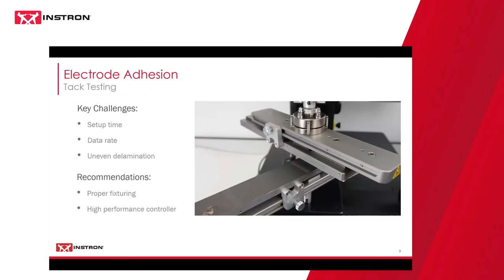So another type of electrode adhesion testing that we've seen is tack testing. As of lately, I'm yet to see tack testing take over as a primary quality control test, but it has been seen as a secondary one. As far as primary goes, usually a primary would be the 90 or 180-degree peel test for quality control or understanding the properties of your electrode adhesion. But tack testing has definitely been coming in as a secondary one.